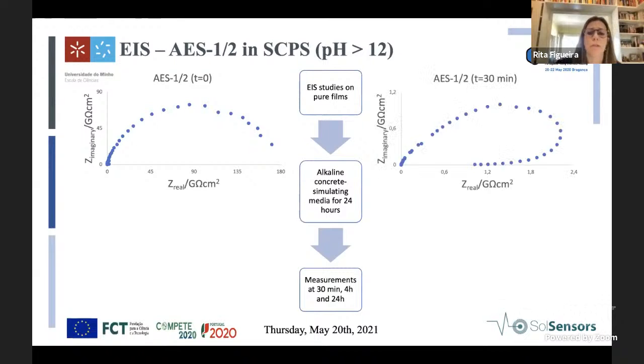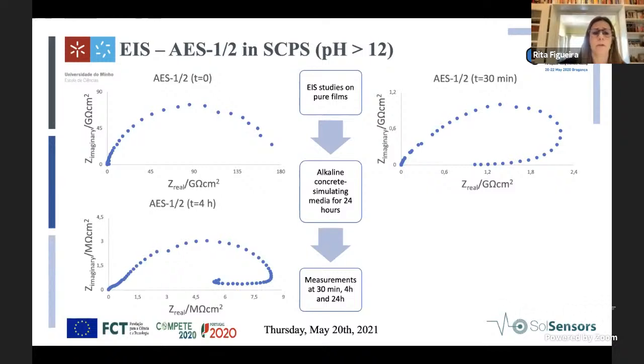Then we measured and analyzed by electrochemical impedance spectroscopy in simulated concrete pore solutions. A simulated concrete pore solution is a solution that simulates the pH inside the pores of concrete, where we use a saturated solution of calcium hydroxide and potassium hydroxide. And it's a pH above 12.